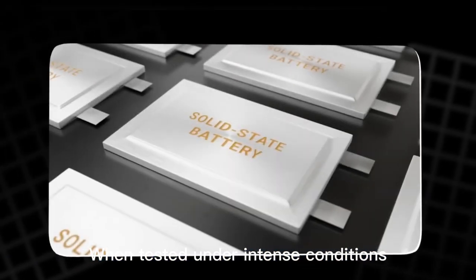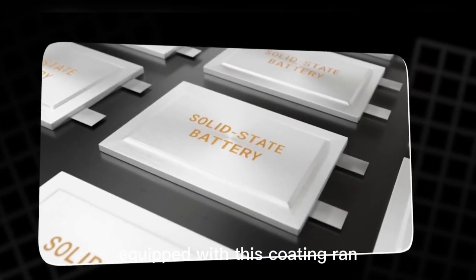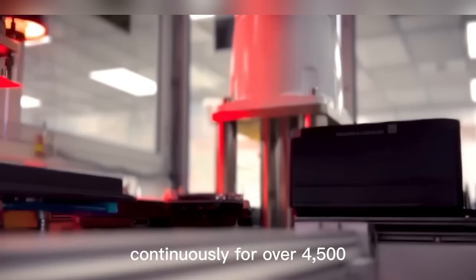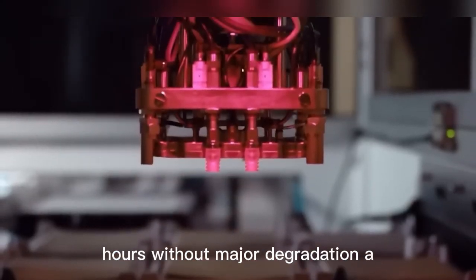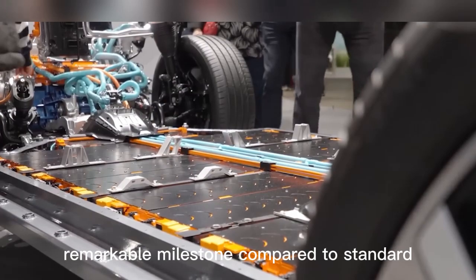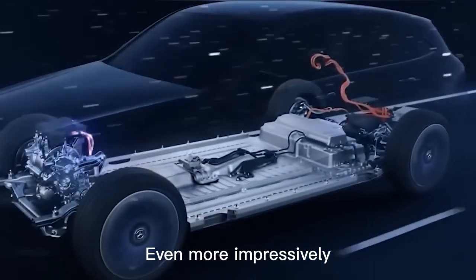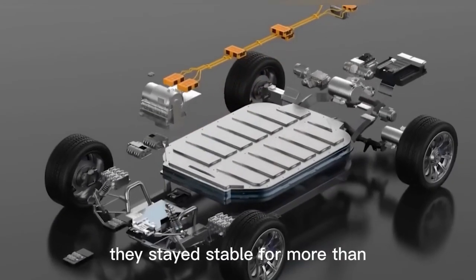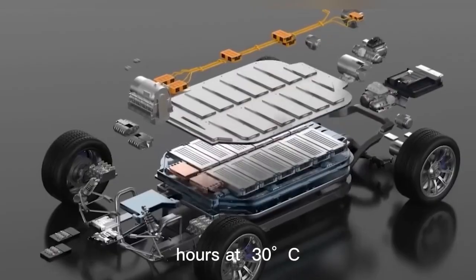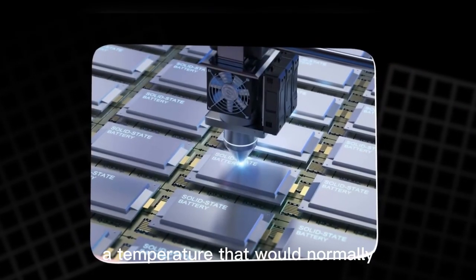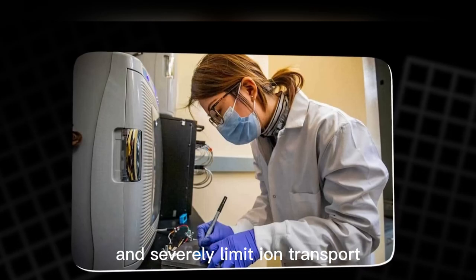When tested under intense conditions, the batteries equipped with this coating ran continuously for over 4,500 hours without major degradation, a remarkable milestone compared to standard solid-state cells. Even more impressively, they stayed stable for more than 7,000 hours at -30 degrees Celsius, a temperature that would normally cripple most batteries and severely limit ion transport efficiency.